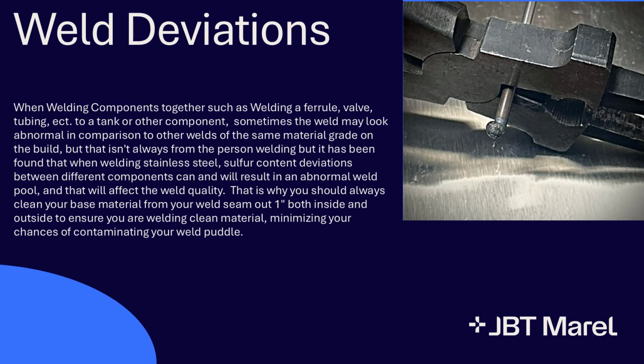Weld deviations. Another key point in letting outside contaminants into your weld puddle when manual welding with filler wire is to make sure that the filler wire stays in the gas flow zone, and if it comes out of the gas flow zone, the operator will be able to tell because the filler wire will ball up on the end and oxidize almost every time. When this happens, the best thing to do is to cut off the oxidized gray or black portion of the filler wire. If the oxidized wire is then reintroduced into your weldment, the weld puddle may act as if it wants to go all different directions, making it hard to control the progression forward of the weld puddle and ultimately damaging the oxide layer.